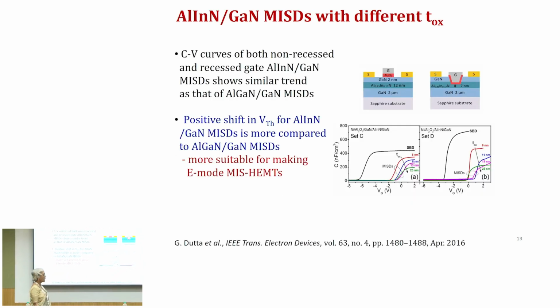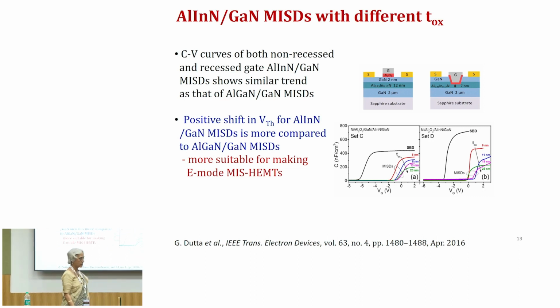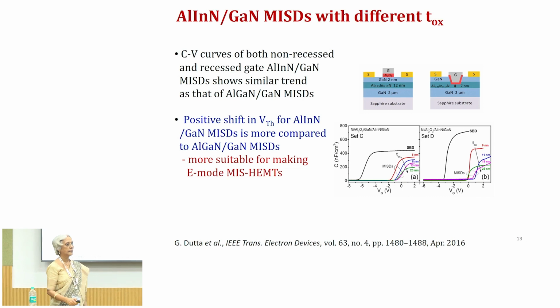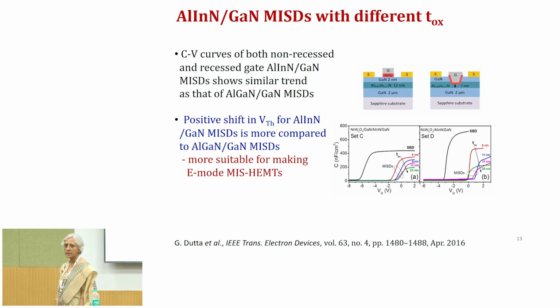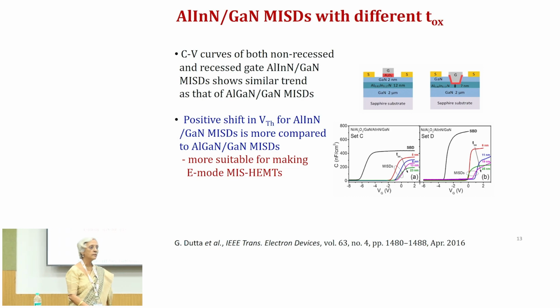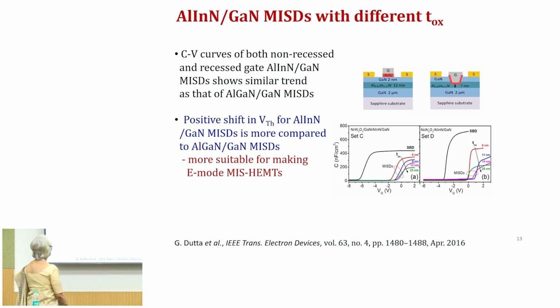So, we try to make HEMTs or MISHEMTs rather with different gate dielectric thickness. As I said, our idea was that if we increase the gate oxide thickness, then we should be able to get a positive threshold voltage. At the same time, we also used a recessed gate aluminum indium nitride gallium nitride, because as I said, if you have a thinner barrier, then also you are supposed to get a positive threshold voltage.